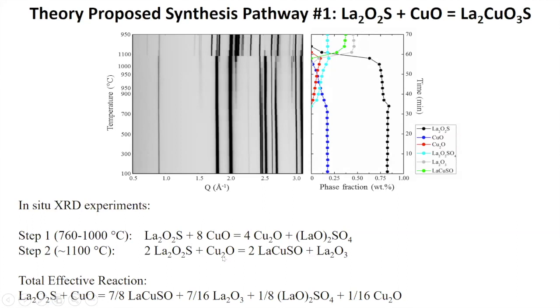The second stage of the reaction happens at something like 1,000 degrees, 1,100 degrees, and that's the copper one oxide breaks down, forms with this compound to make the end product, which is lanthanum copper sulfur oxygen plus excess lanthanum oxide. So this didn't go exactly the way we had hoped. The total effective reaction is shown here, which gives you an idea of what the yields are in the reaction. And so essentially we form this quaternary compound instead of the quaternary compound we were after. And the downside of that is also that this is a copper 1 plus system, not a copper 2 plus system. So presumably not that interesting.